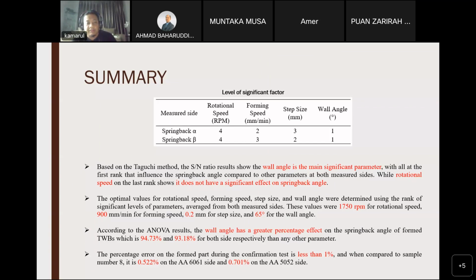The percentage error on the formed part during the confirmation test is less than 1%. The last point is the comparison between the confirmation test sample and sample number 8. The percentage error from the confirmation test compared to sample number 8 is just a difference of 0.522% for the 6061 sample, and only 0.701% for the 5052 side. This means both major sides have a slight difference, and that difference is less than 1%.